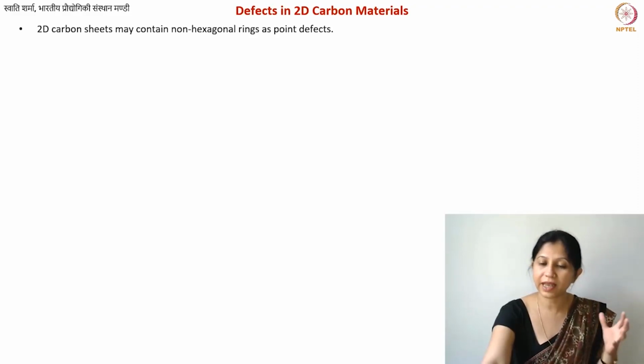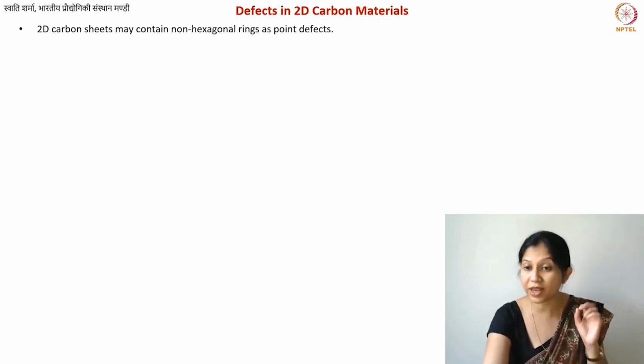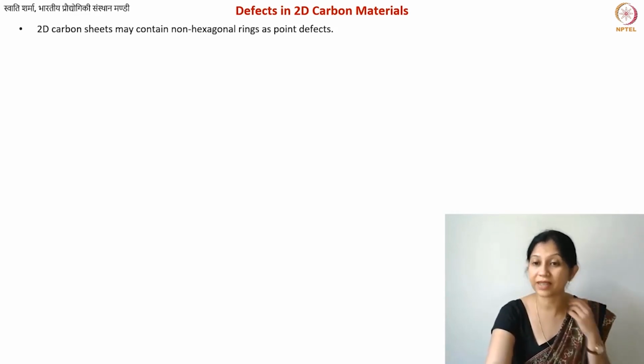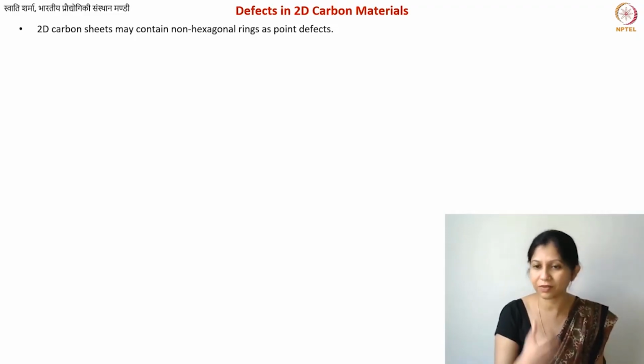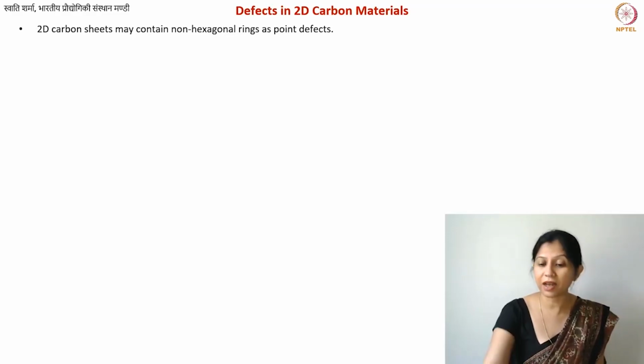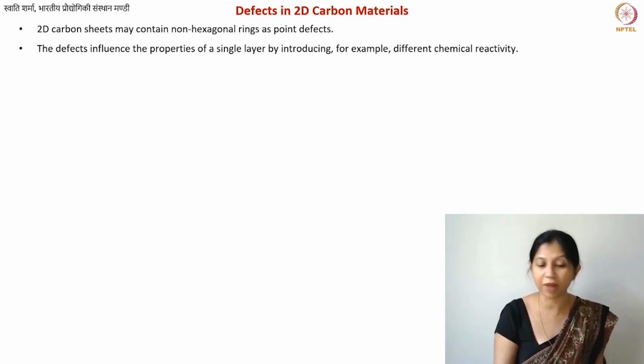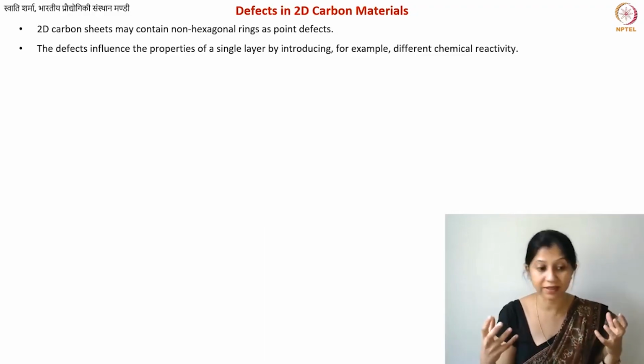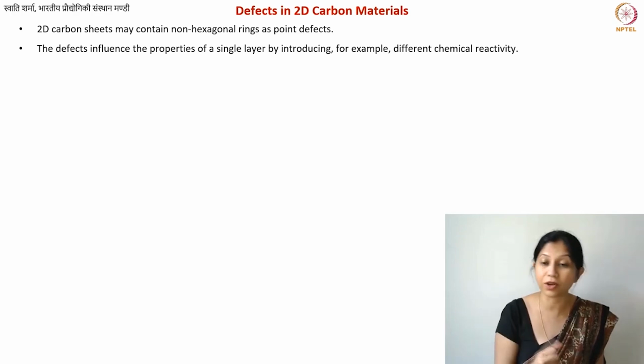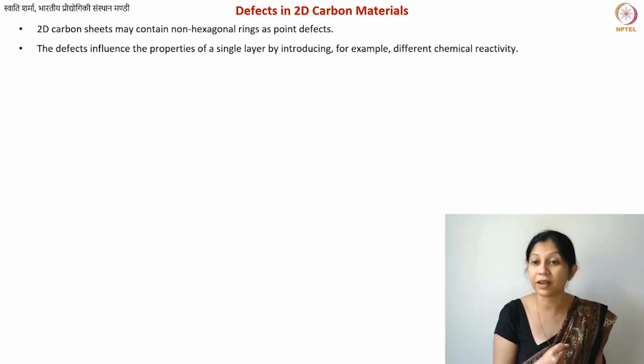So we know that in the bulk carbons, as well as sometimes when you're trying to make graphene, you may get these hexagonal carbon sheets which contain non-hexagonal structures. Okay, so this is when we are talking about 2D carbon sheets. And often what happens is when you're manufacturing graphene using the CVD technique that we have discussed in detail, it's already very difficult to control the geometry or the size of your graphene, also the layer thickness. Maybe you will not get single layers, you will get multi-layer graphene, you will get few layer graphene. And in that case, the structures that you obtain often contain a lot of defects, so to say.